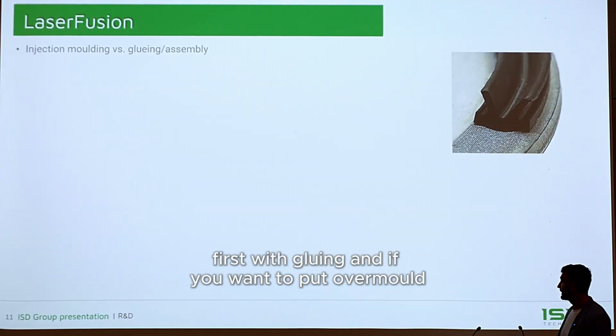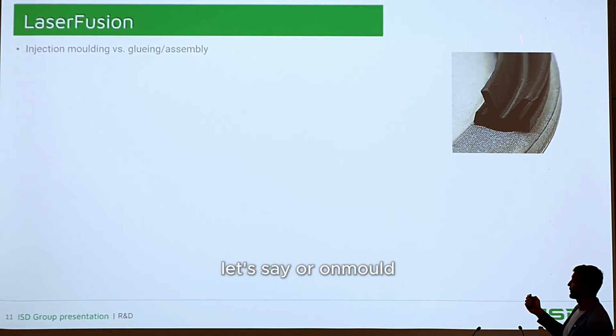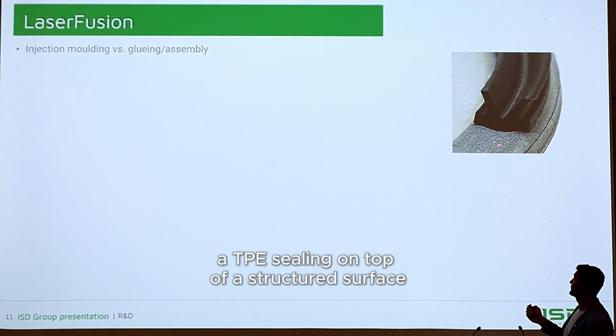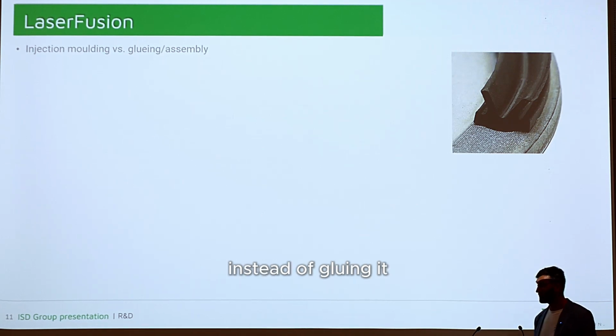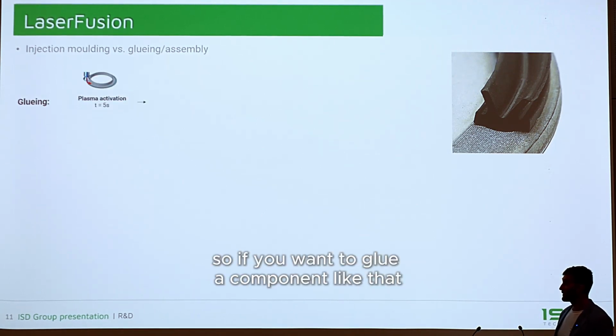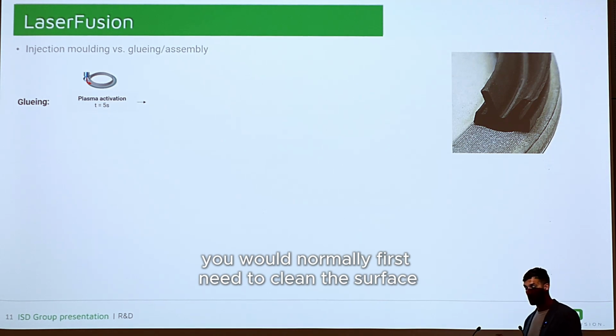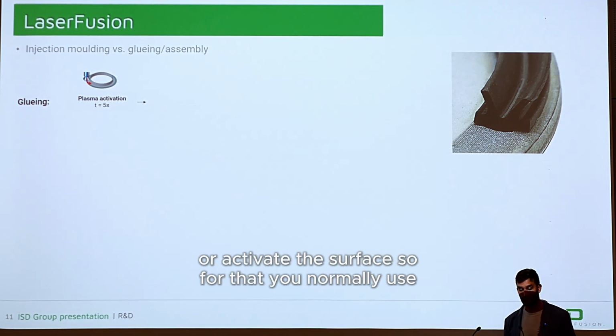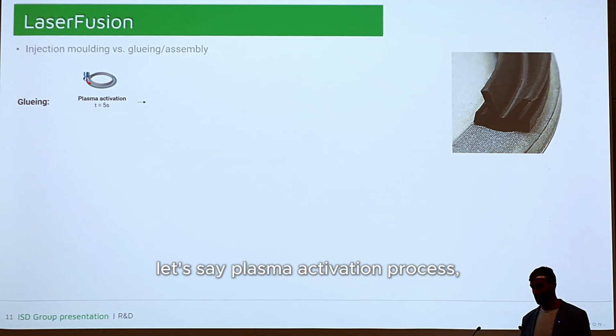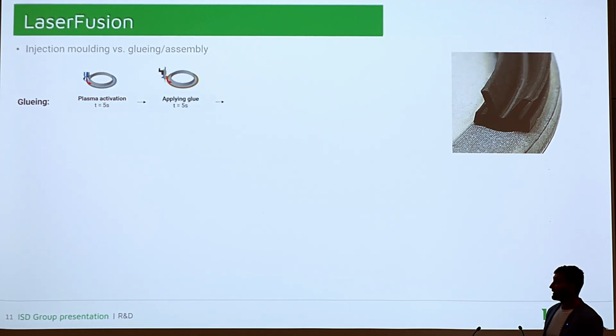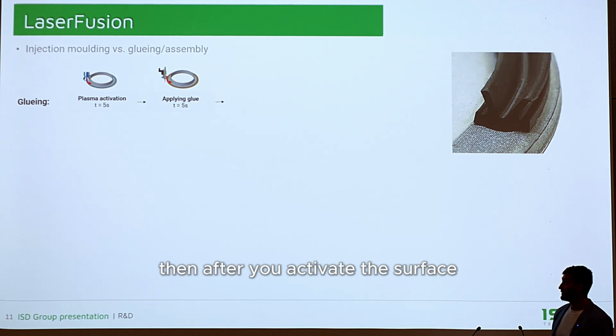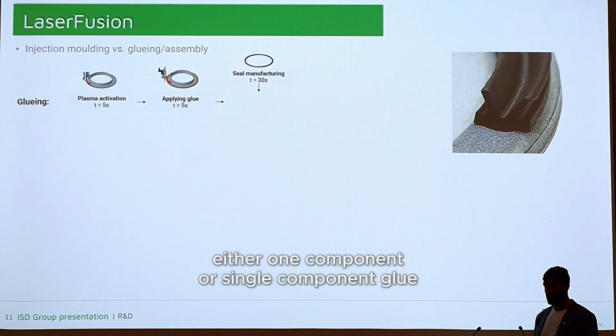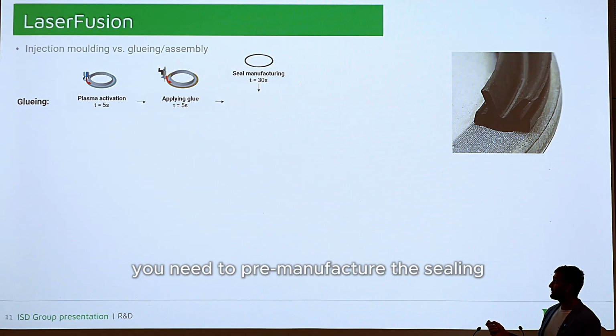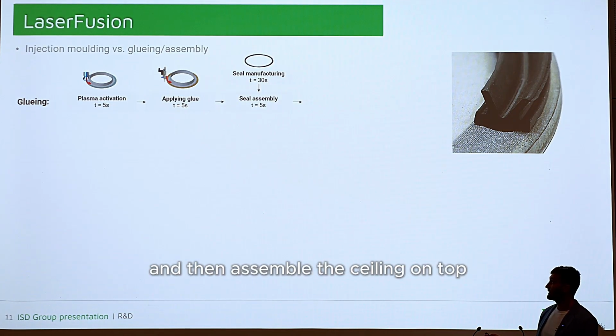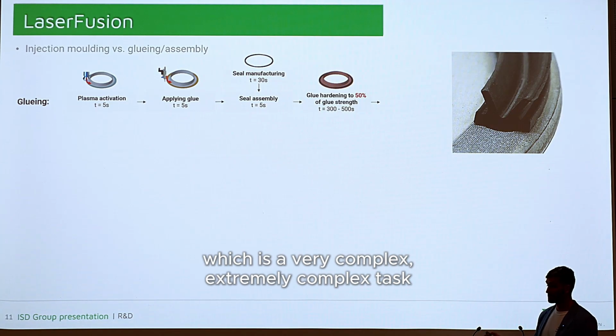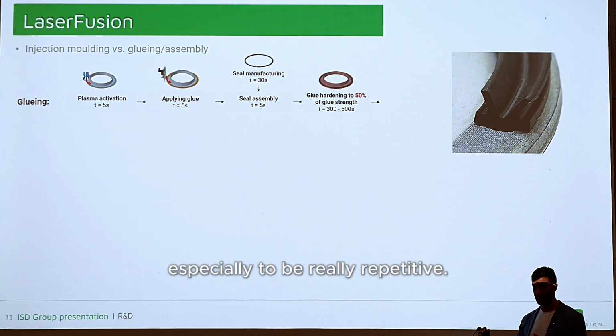Now if you look at the overall process scheme in comparison, first with gluing, if you want to overmold, or onmold, a TPE sealing on top of a structured surface instead of gluing it. If you want to glue a component like that, you would normally first need to clean or activate the surface. For that, you normally use a plasma activation process. Then after you activate the surface, you apply the glue, either one component or two component glue. You need to pre-manufacture the sealing and then assemble the sealing on top, which is an extremely complex task, especially to make it really repeatable.